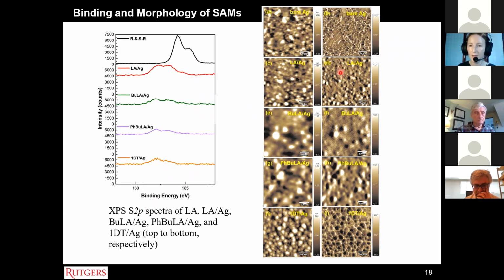You can see the surface morphology here, which was measured by my student Hemant Madali, that there's an increase in the surface roughness as well as an increase in grain size when we apply the self-assembled monolayers to the bare silver. Overall, there's some consistency between the degree of roughness and coverage of the self-assembled monolayers, although in the lipoic acid case here, we see better coverage compared to the 1-decane thiol and the butyl lipoic acid.